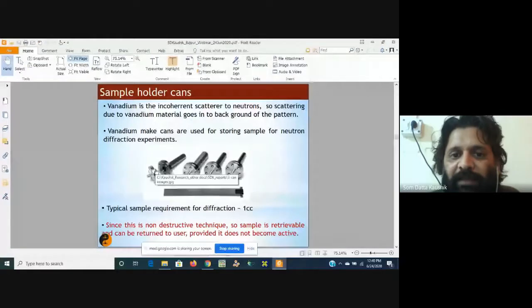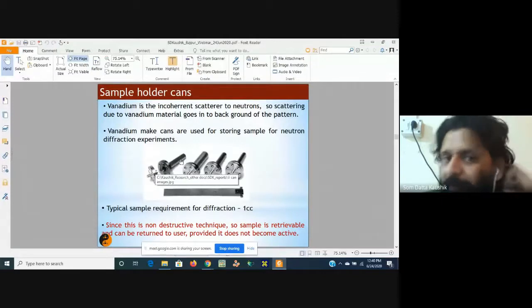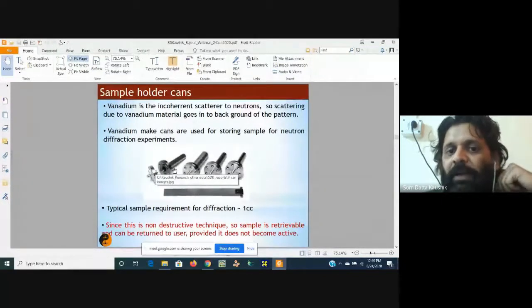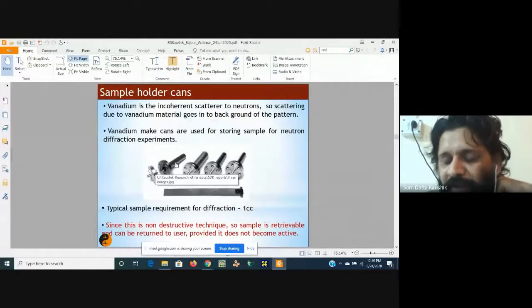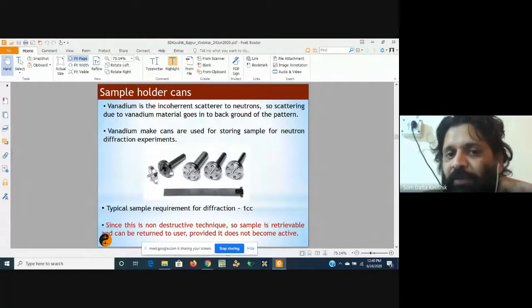And these are basically your sample cans. We put the sample in these vanadium cans. Why do we use vanadium? Because vanadium is an incoherent scatterer of neutrons. So the scattered neutrons from the vanadium will go into the background. It will not form a peak. So whatever data is coming will be because of your sample only. There will be no peak because of vanadium. That's why we use a vanadium can.